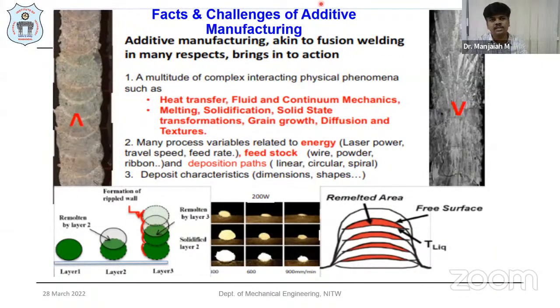Some of the facts and challenges with respect to additive manufacturing: additive manufacturing is akin to fusion welding in many aspects, bringing into action heat transfer, fluid dynamics, and continuum mechanics, how melting takes place, solidification, and how much solid state transformation takes place for grain growth and diffusion of the texture and all. There are many process variables which relate to the energy density, that is laser power, travel speed, feed rate, as well as feedstock, that is wire, ribbon, or powder we are using. This will add to the complexity of the fabrication.